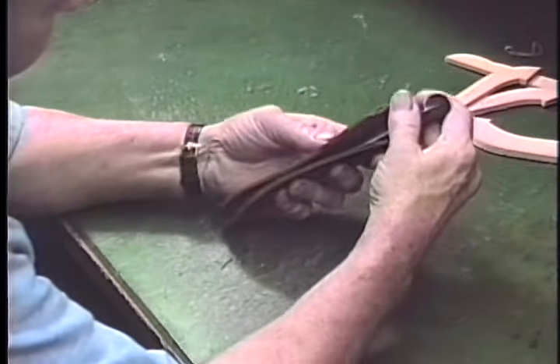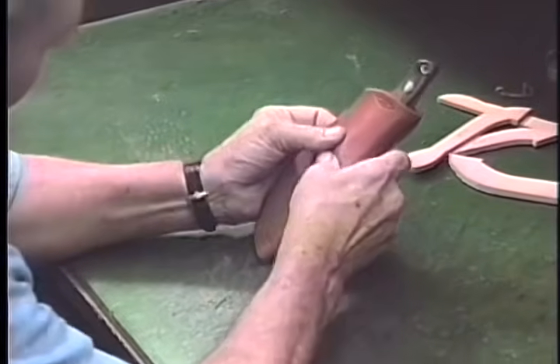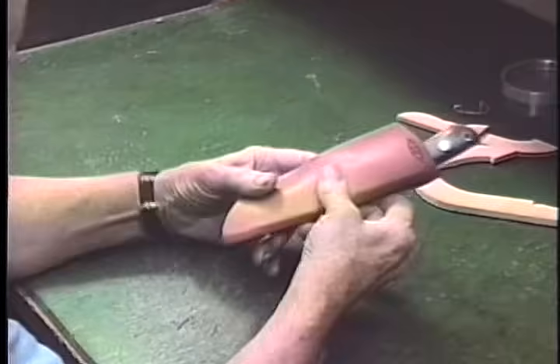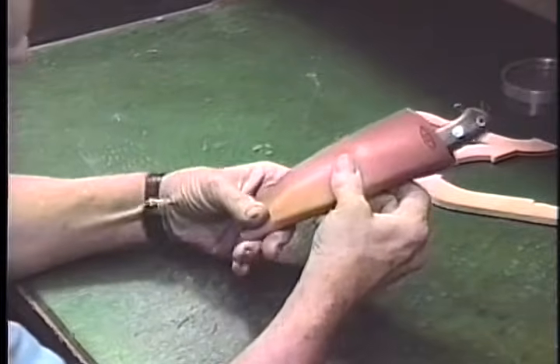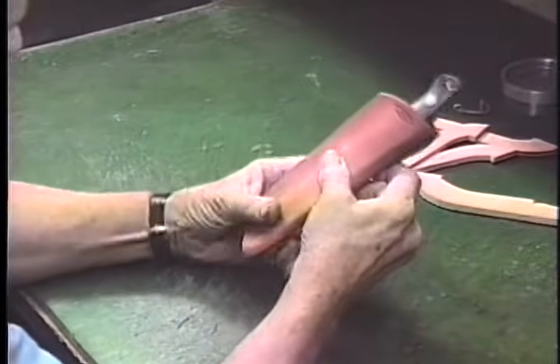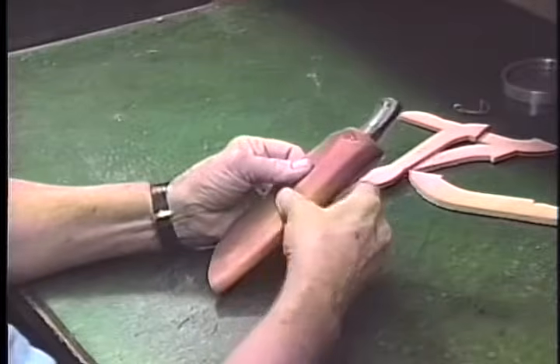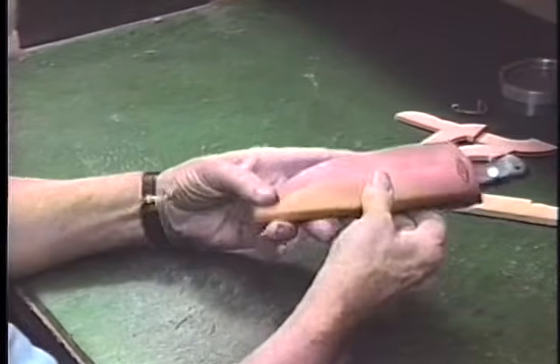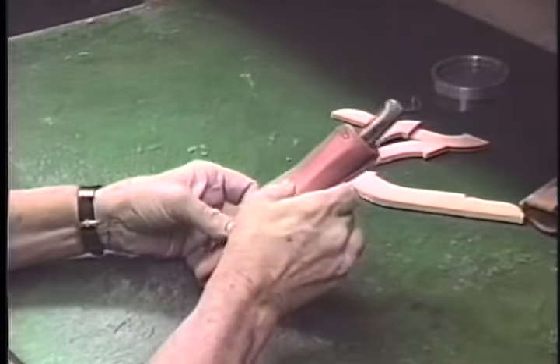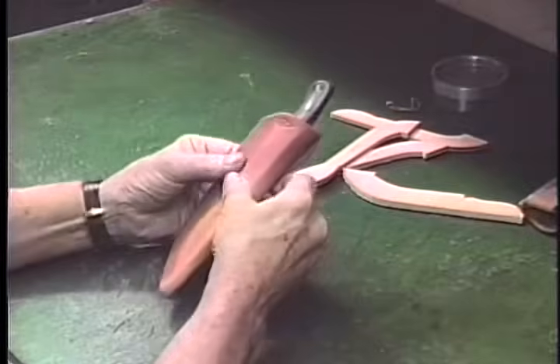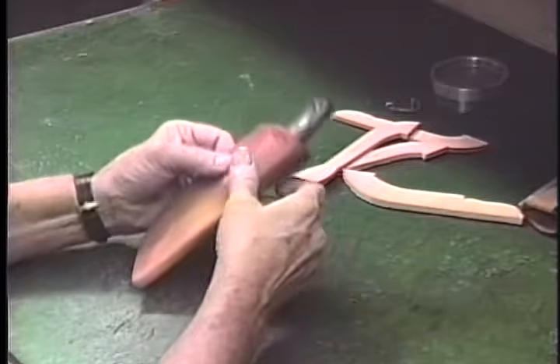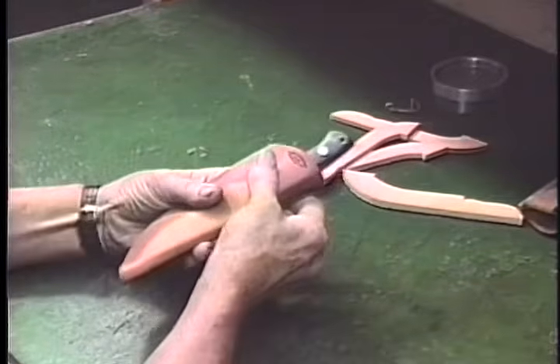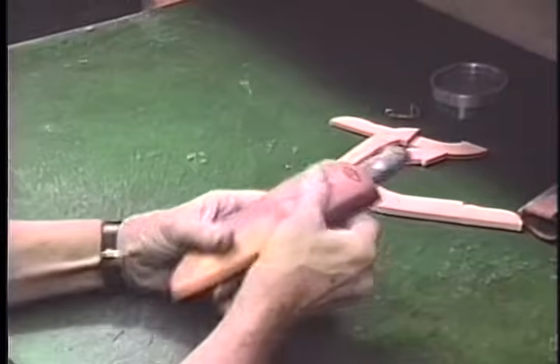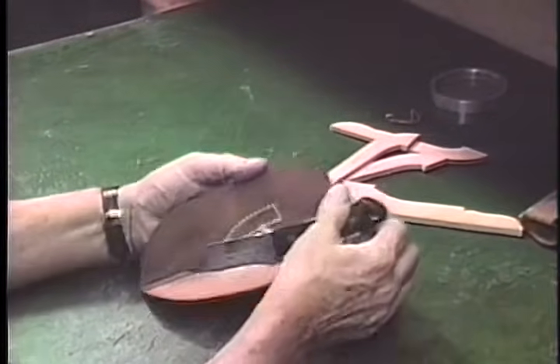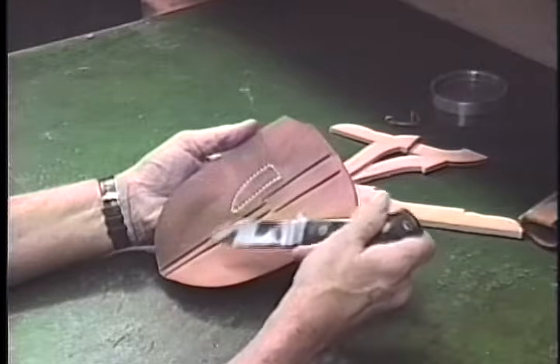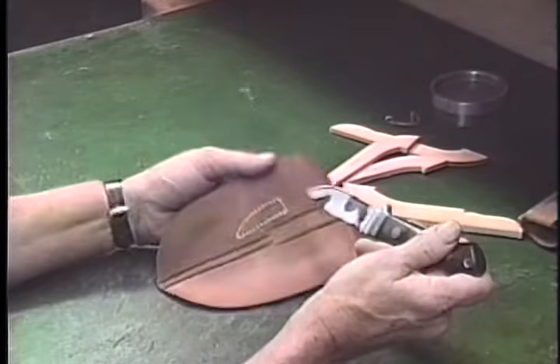We set it down in there about like that. We hold it shut, and we, with our thumb, we press it into the leather, push the leather down around the knife. Now this is called the wet molding process. And it's the only way there is to get a really good, special, custom, snug fit for the knife you're putting a sheath around. These knives, although they're very, very closely alike, they are not interchangeable. And when we open it up, we'll see the line of the blade on the back side and the front side of that sheath. And there's the reverse pattern of the handle.